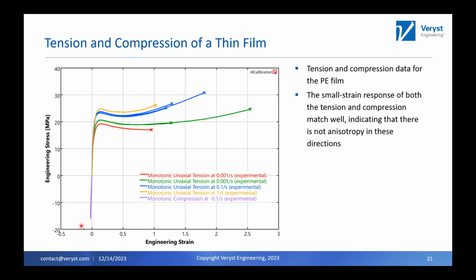And then if we look at all the data together, you can see here that these look pretty similar. I don't have a zoom in here, but there's not really any difference in the slope here at the small strain, which is something that you might expect for these films because these are extruded. But in this particular film, we did not find that there was any anisotropy in the film due to testing in different directions in plane or in plane versus through thickness.